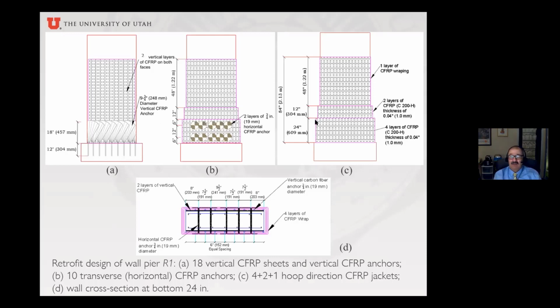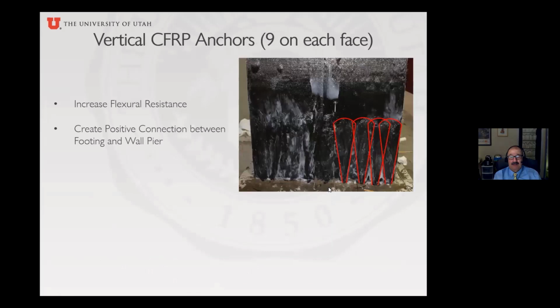There are 4 layers for the first 2 feet, 2 layers for the 1 foot above, and then the other 4 feet is just 1 layer. So there's quite a few layers here, but the bottom 2 feet is reinforced pretty heavily. So here you can see the anchors that are sticking up about 18 inches, and they overlap each other. There was 9 of these on each side of the wall.